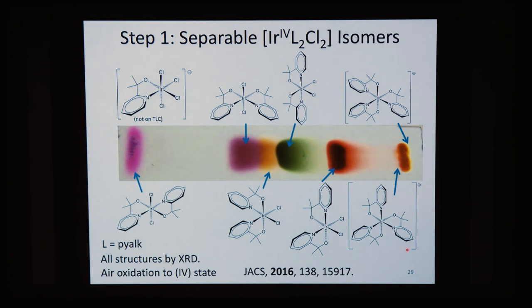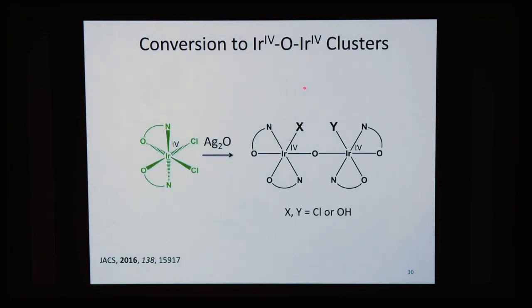Now, the green isomer is the important one because it has all the anionic ligands in the same plane. And if we remember Dimitar's hypothesis, this should provide the most stabilization for the high oxidation states. And if we treat the green isomer with silver oxide, we get the bridging oxo of just one isomer, which can be crystallographically characterized. And if we have a short reaction time, X and Y remain chloride. But if we go for a long time, they are replaced by OH hydroxide.